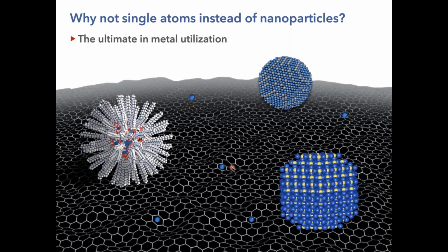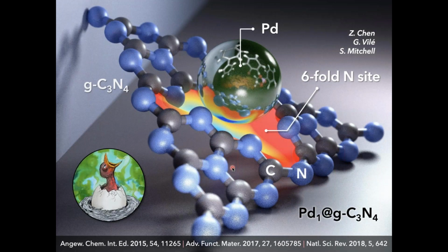If you look at single atoms, always the critical thing is how stable these single atoms are under reaction conditions. So you want to avoid any sintering during reaction conditions. And for that, it's very important to design the right host. So our work has very much focused in the beginning on carbon nitrides, which contain these six-fold nitrogen coordination sites, which are able to stabilize single atoms.